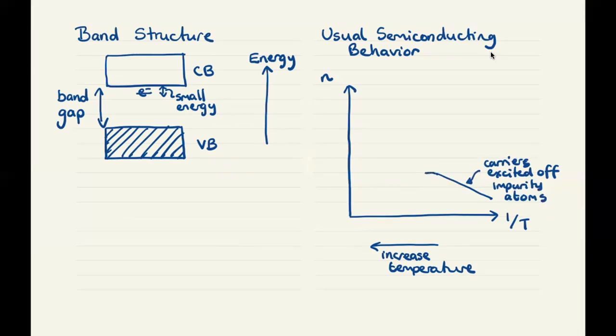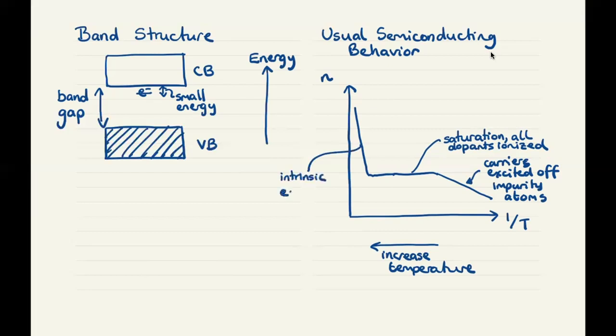And then there's a region of temperature. As the temperature increases, the number of carriers doesn't really go up very much. This is the saturation region, where all the dopants are ionized. All of the phosphorus ions have already lost their electrons into the conduction band. Until a very high temperature, at temperatures corresponding to the band gap, then the carrier concentration goes up again. And this is what's called the intrinsic region, where we have electron hole excitation across the gap.